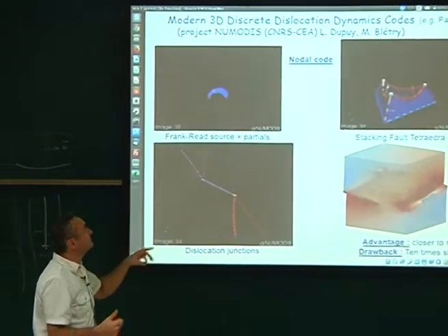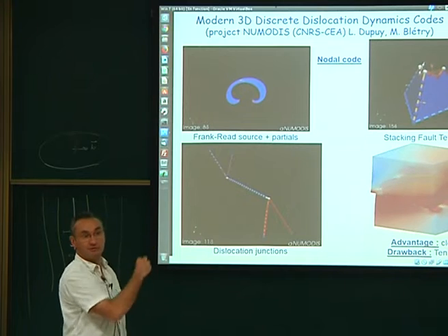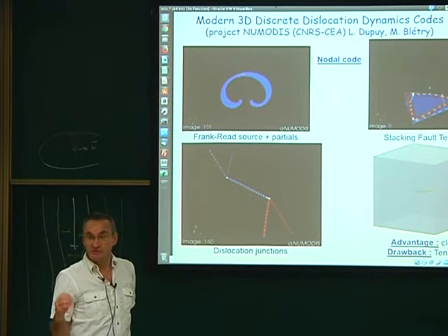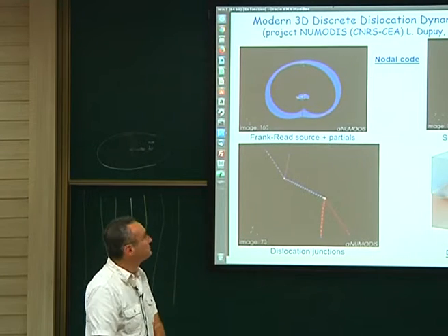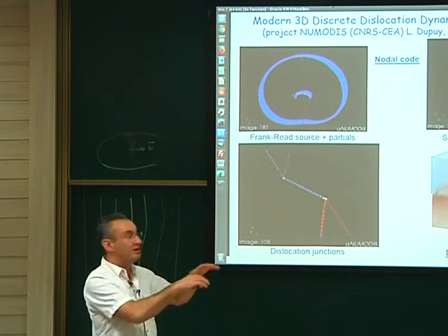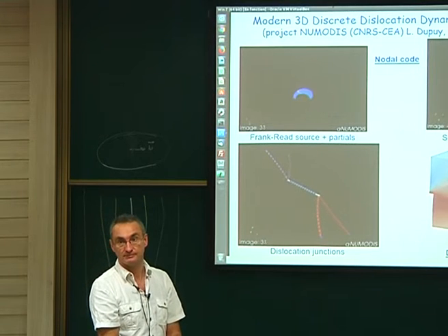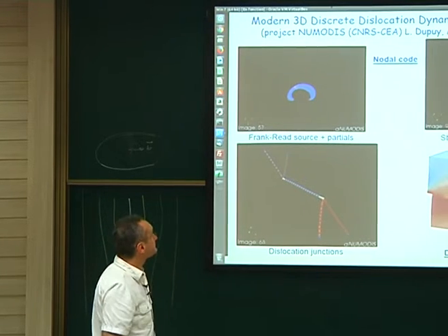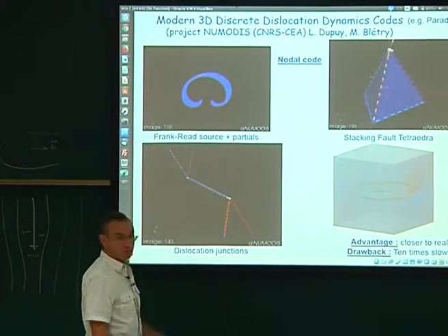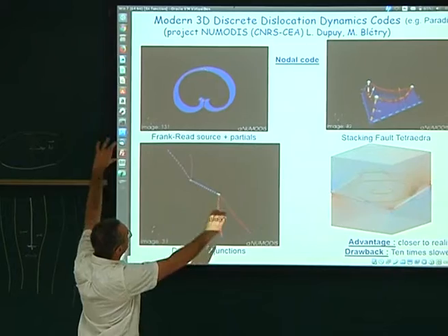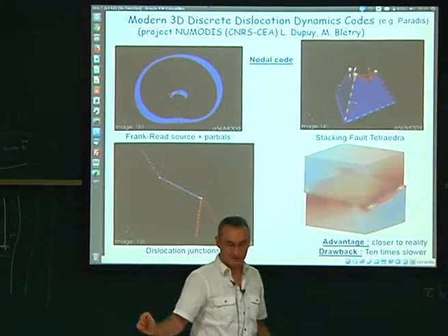And so this is the first answer. And the second answer: here you can see clearly that there is no pure screw. And then you will have diffusion of atoms everywhere, actually. To answer your question, you should maybe ask experts of the field, but I would say that diffusion theoretically could happen everywhere as soon as your dislocation is dissociated, because you will have edge components everywhere. Okay? You see my point? So this was just to illustrate that on the top left. You clearly see the two things: first, this elongation, and this non-continuous thickness of the stacking fault.